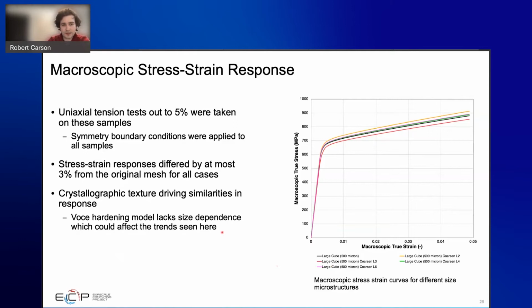However, as part of this project, we're also interested in potentially looking at porosity type models or parameterized porosity type models with our macroscopic simulations. Because of that, we want to use something that's not super coarse, because we want to capture the distribution of our hydrostatic stress within our material decently well. And so we really don't want to coarsen it so much. So that answers the question about our RVE.